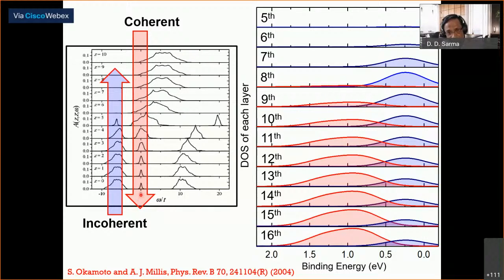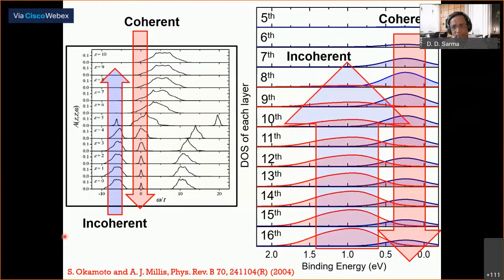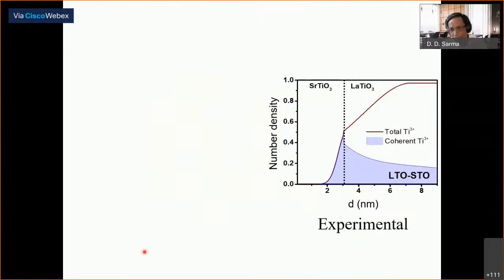The coherent feature intensity should first increase and then decrease, because remember, I'm looking at that small part. It first increases and then decreases. It's highest at the interface region. It is exactly the same description that you have found here. And quantitatively also, if I map out the coherent intensity, which is this green part I showed you earlier, this is the total electron density, how it is distributed. And this is how the coherent to incoherent intensity ratio varies.